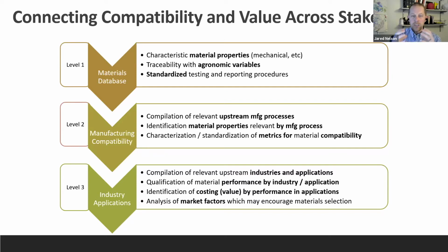What was missing was a good understanding of how to use these materials, a good understanding of the characteristic material properties associated with these materials, how to trace the agronomic variables. So for example, I said we weren't going to talk at all about how this stuff is grown. Well, you could have the same field, you could plant it in the same way, you could use the same seed 2 years in a row, but you can't predict the weather. You can't predict what's going to happen after you harvest this material and you leave it in the field and you ret it, which is a process by which bacteria come in and separate that bast fiber from that herd material. Those things aren't really as controllable as we would like. And so therefore, we have to trace and be able to understand how differences impact the end fiber. Furthermore, there's no standardized testing or reporting procedures.